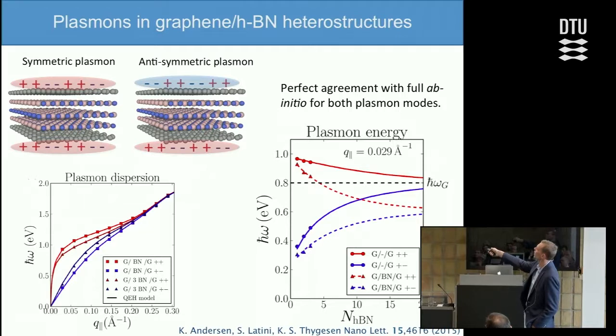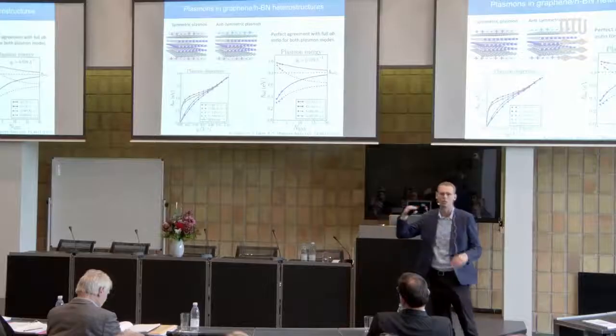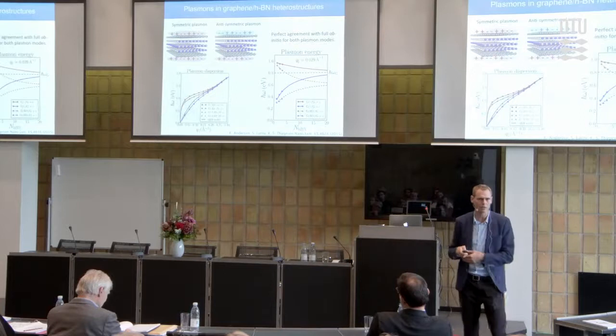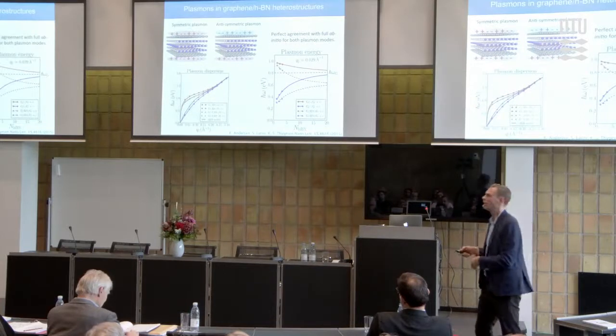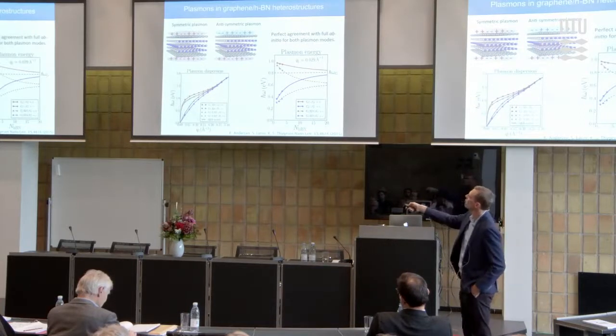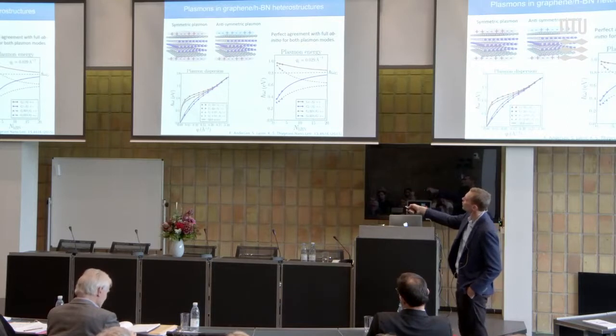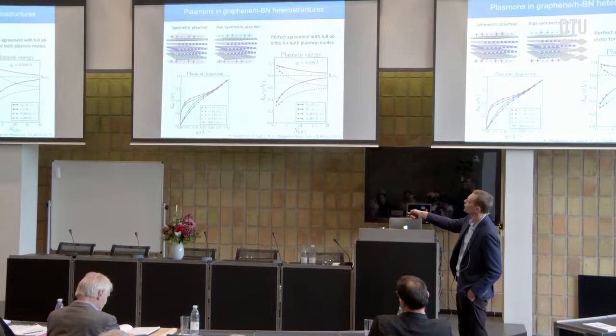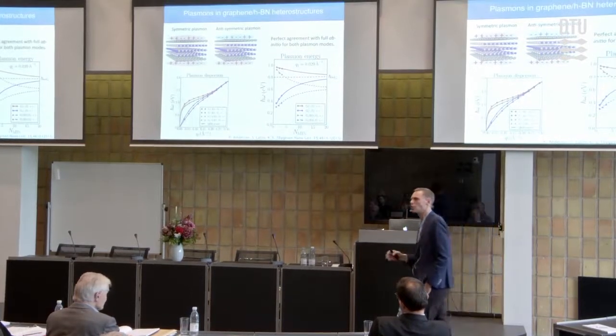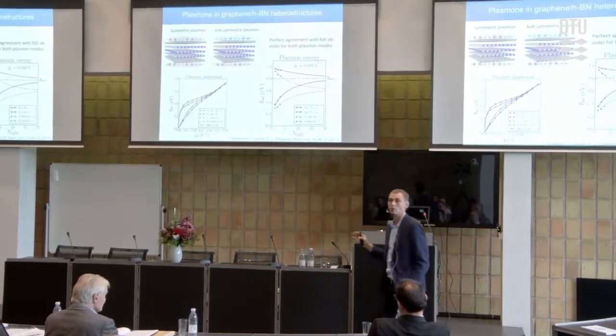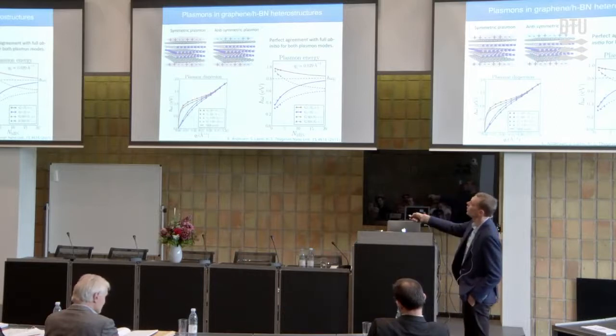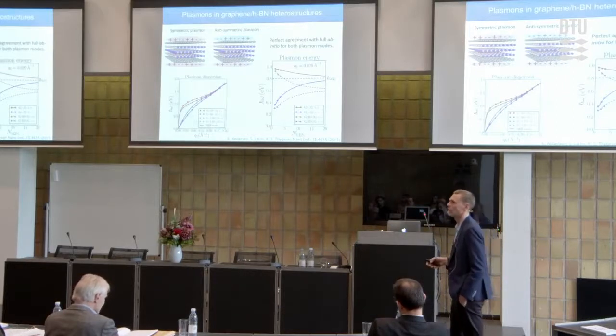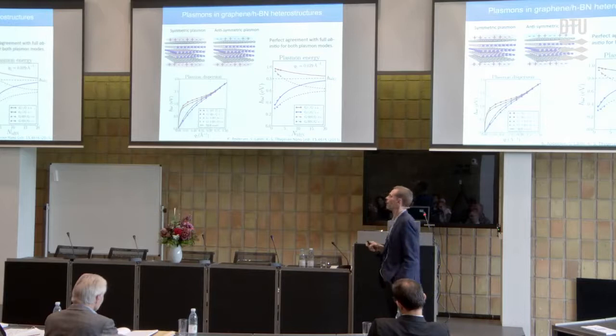One is a symmetric and an antisymmetric combination of the sheet plasmons in the graphene layers, because they hybridize and interact with each other. What I'm showing here is the plasmon dispersion of the two modes calculated using the QEH model—the full lines—and the symbols are from a full quantum calculation of the entire heterostructure. The agreement here is, I would say, almost too good.